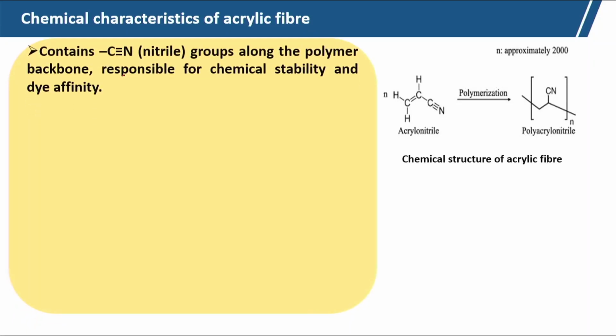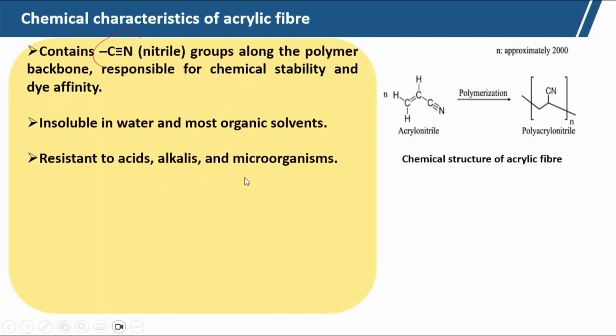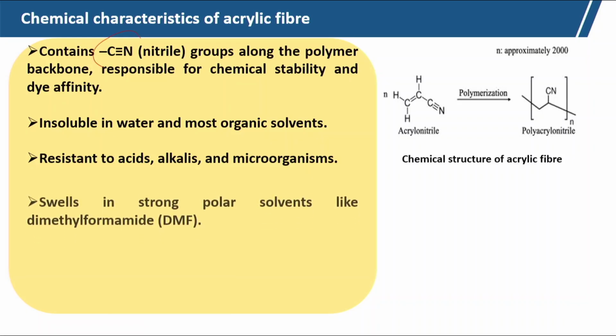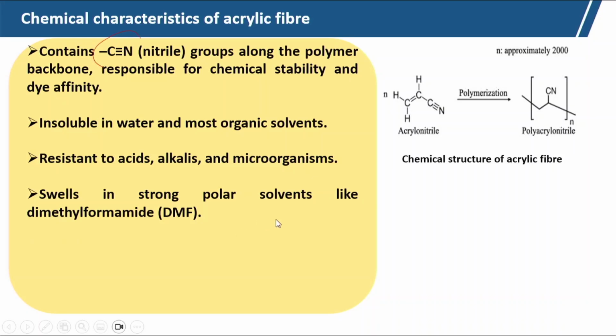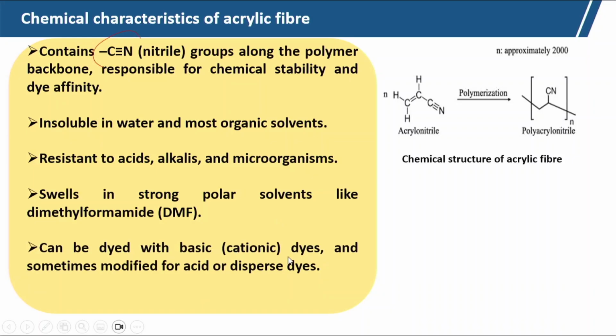And chemical characteristics, if you see here, it contains the C triple N bond, the CN group, along with the polymer backbone, responsible for chemical stability and dye affinity. So, the triple bond is actually the nitrile bond, which is responsible for chemical stability. Insoluble in water and most organic solvents. This is chemical protection we can use, resistant to acid, alkali and microorganisms. It does not get affected by acid, alkali or microorganisms. Swells in strong polar solvents like DMF, can be dyed with basic cationic dye, and sometimes modified for acid or disperse dyes.